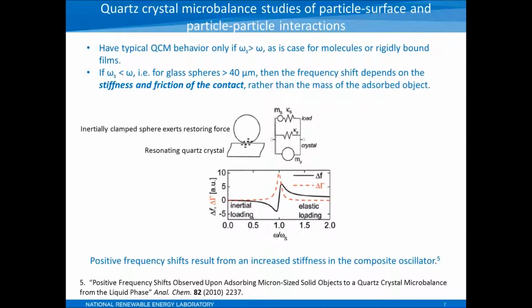Thanks to the World Wide Web, I almost immediately came across a paper that explained this, and it's interesting to me that it's a fairly recent paper. It's from 2010. I would have thought that decades ago someone would have figured this out, but it's a relatively recent result. So it turns out that you have typical QCM behavior, and when I say typical, I mean that you put particles on something and the frequency decreases only if the resonant frequency omega s of the particle itself is much larger than the resonant frequency omega of the resonator. So that's the case for molecules or very rigidly bound films.